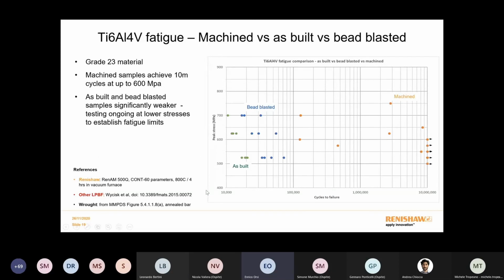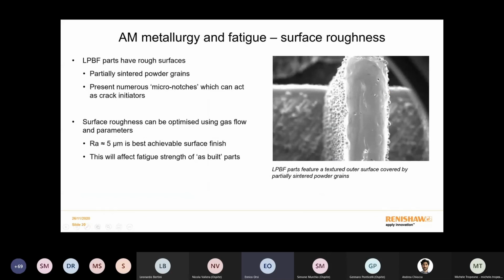One aspect that is extremely important for the fatigue in AM processes is the surface finish, as in any process, but specifically because AM will not return parts that have a very high polish surface. Normally, the parts that come out of the AM process have rough surfaces, with parts and powder beads attached to the surface. This will generate a lot of micro notches on the surface that can lead to defects. So there is a big difference between parts that have been tested as built or after machining. As in some cases, parts need to be used as built, this is definitely a field of research to achieve the best possible surface quality to improve the fatigue resistance.